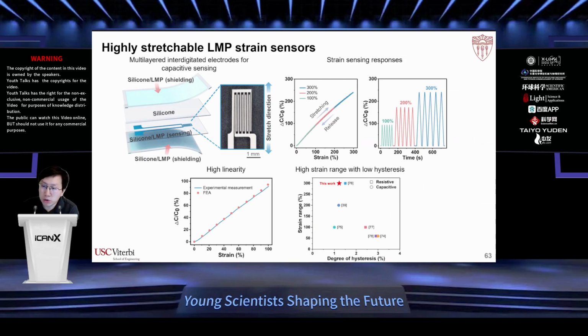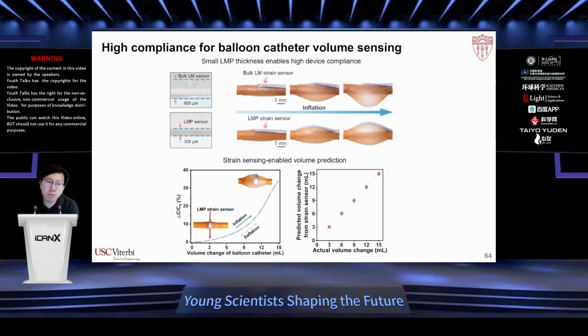It can achieve a pretty good combination of strain range and hysteresis. And more importantly, because the liquid metal layer is very thin, we don't have to use very thick microfluidic channels, so we can make the sensor very thin and soft. Because of the low stiffness, we can integrate this strain sensor onto a very soft, deformable balloon catheter without affecting its intrinsic mechanical properties. So we can use the strain sensor data to predict the volume of the balloon.